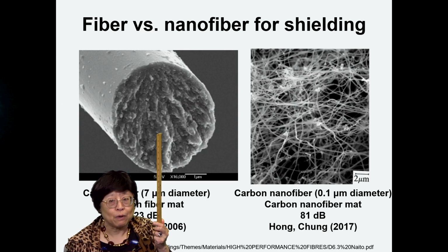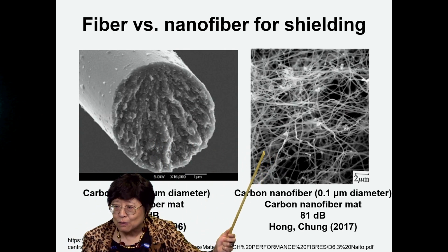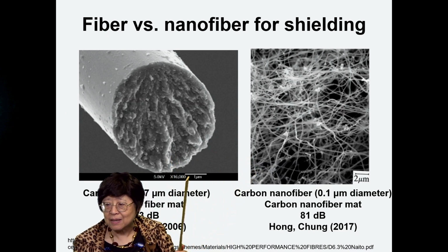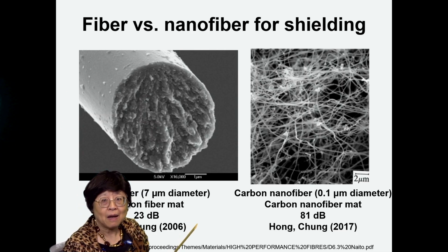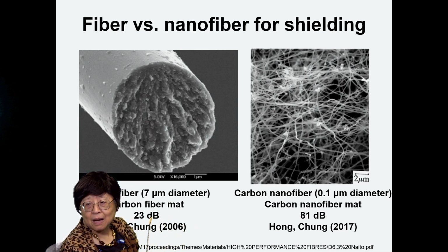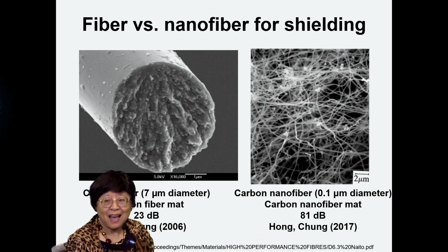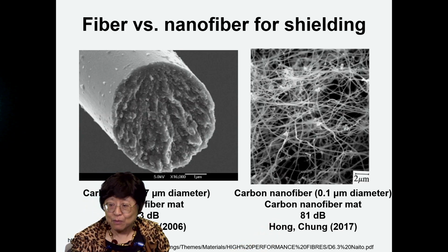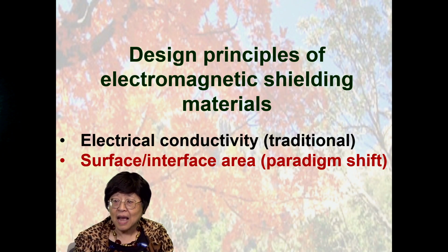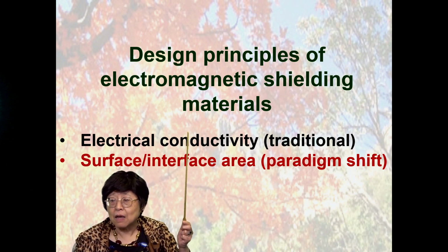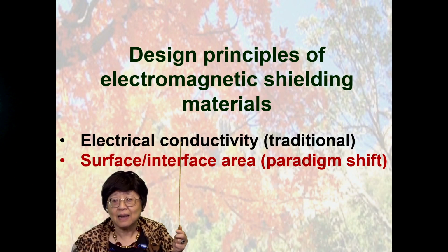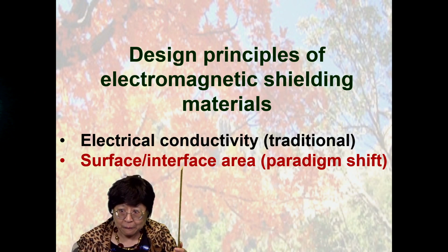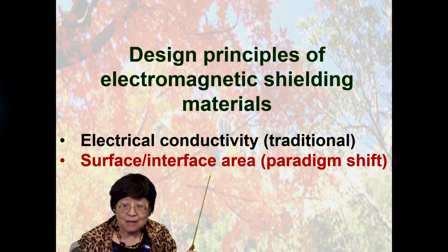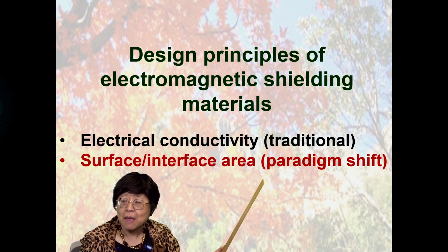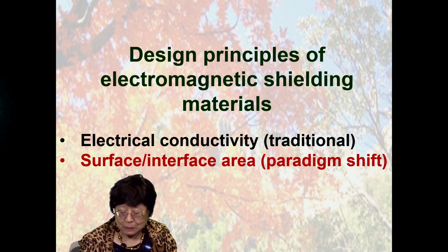Now, this is microfiber, 7 micron diameter. This is carbon nanofiber, 0.1 micron diameter. We put both in a polymer matrix at similar loading, and we find that with the microfiber, the usual fiber, it is 23 dB. With the nanofiber, it's 81 dB. So really, having tiny size, in this case tiny diameter, really helps due to the skin effect. The design principles of shielding materials have always long been one thing, which is high electrical conductivity. But I put forth a second principle, namely we want a high surface or interface area due to the skin effect. And that caused a paradigm shift in the design of these materials.